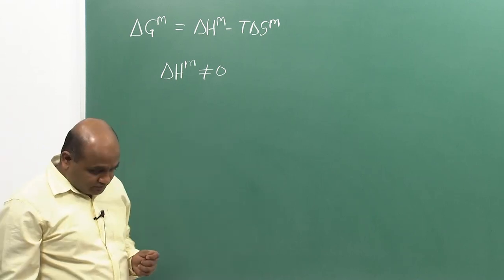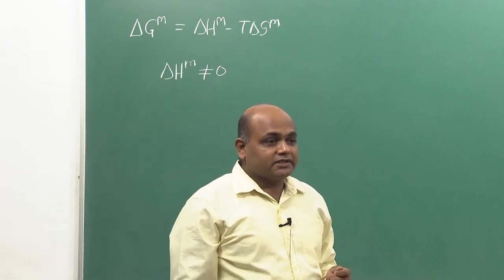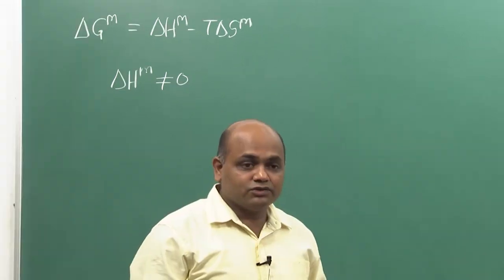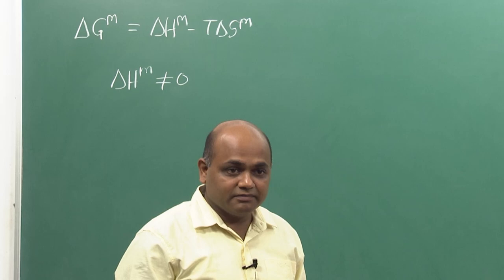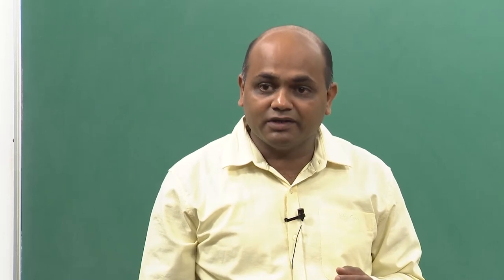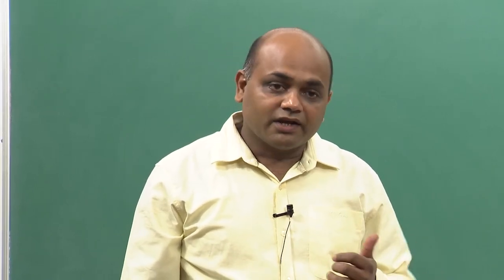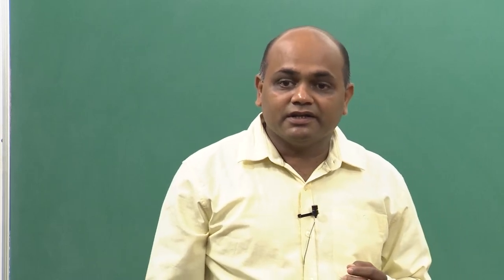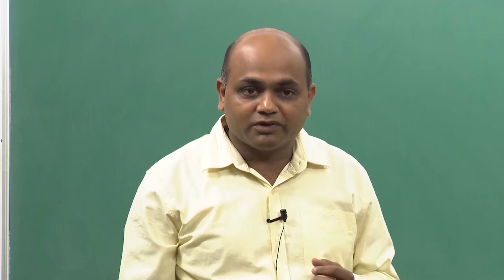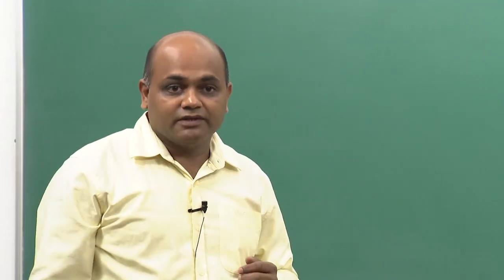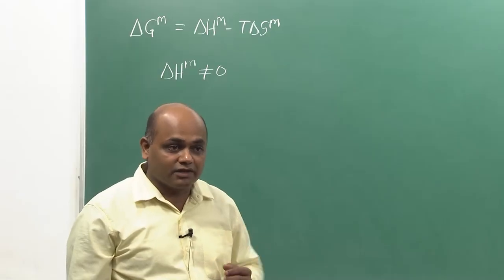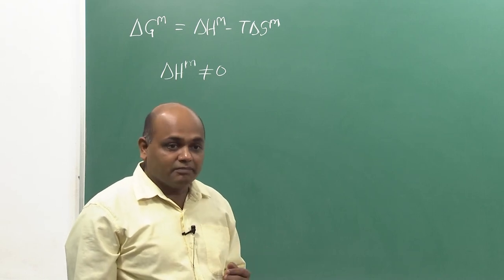Now, when AA, BB and AB interactions are not the same, then in real solutions, the mixing will not be random, right? Because there will be some preference for the nearest neighbor pairs. For example, if AB bonds are stronger than AA and BB bonds, then there will be a tendency to maximize AB bonds. On the other hand, if AB bonds are weaker, there will be a tendency to form AA and BB bonds and minimize the number of AB bonds, right. So, there will be a kind of short range order associated with the difference in the interactions, and so the mixing process will not be completely random. And so, delta S mixing will not be the same as that for an ideal mixing, where we assume random mixing,